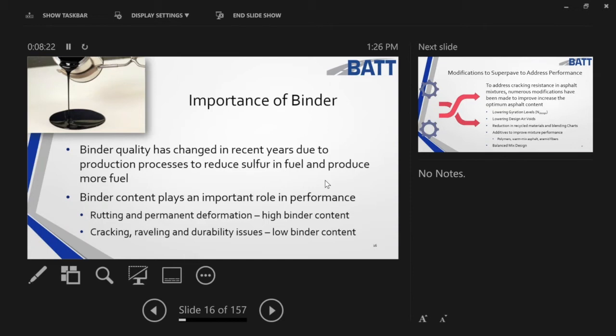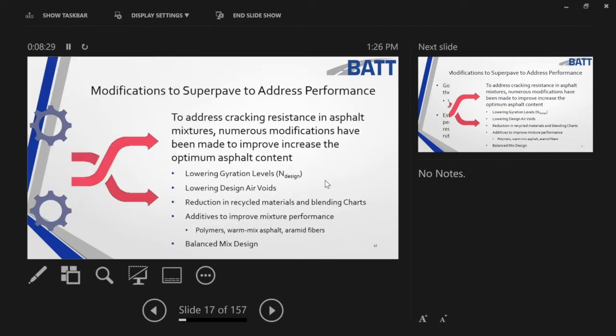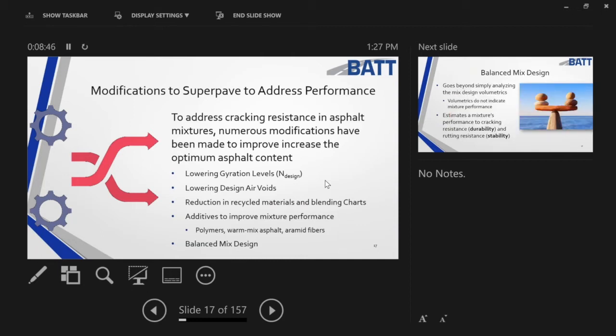But again, this is only one measure. The real change happens in the next slide, which helps us to understand how all of these components go together. Now, I mix the asphalt with the aggregate, and everything was good in the early 2000s, but then we find out our gyration levels are a little bit high. We knew they were high to begin with, but they were up there to help us not fail, as we were trying to keep a nation from having roads that would rut.